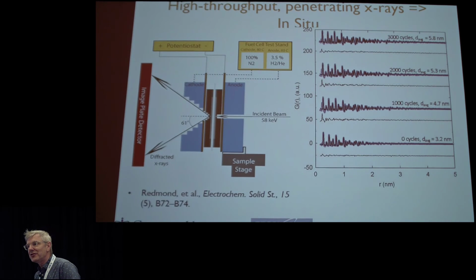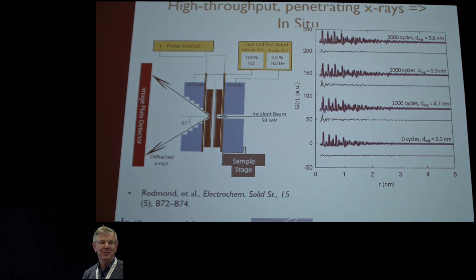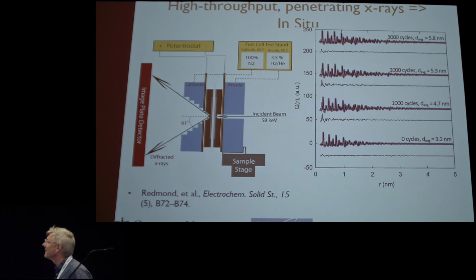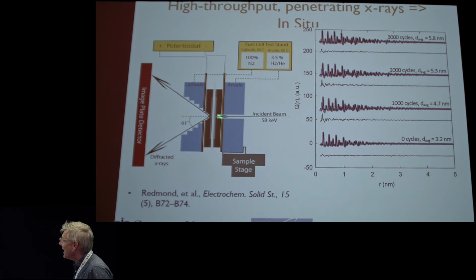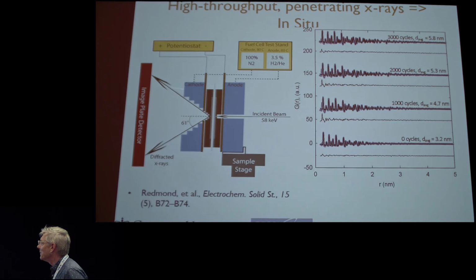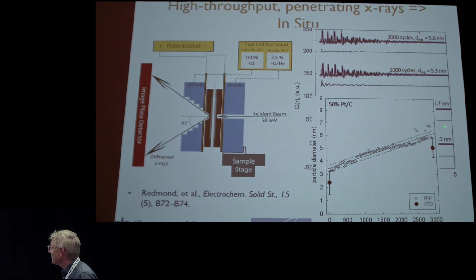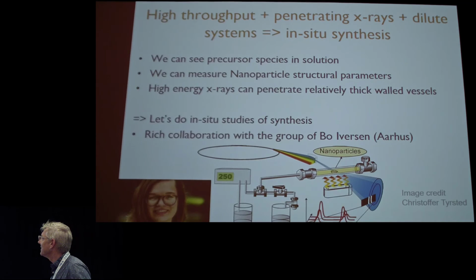What's happening now is I'm starting to show you some of the capabilities that are emerging and pushing into the future. And I'll just go quickly. So we have very penetrating radiation because we use hard X-rays. It means we can do in situ experiments. So this is actually a PEM fuel cell that we can put in the beam and run the PEM fuel cell and then study the local structure. And we can extract the coarsening of platinum nanoparticles as a function of cycling in the PEM fuel cell. So in situ experiments become very, very feasible.